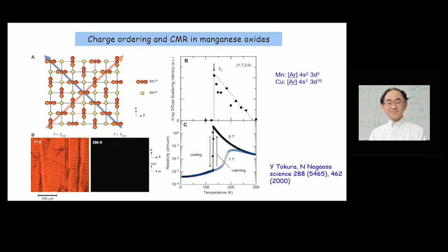Except, in my previous phase diagram, I missed the charge ordering state. The real charge ordering state alternates this pattern of orbital and also the occupancy of eg electrons. This 3+ means we have one eg electron, but 4+ means, if we look at this configuration, we have only the t2g spins here. There are no eg electrons. So these are alternating spins, right?